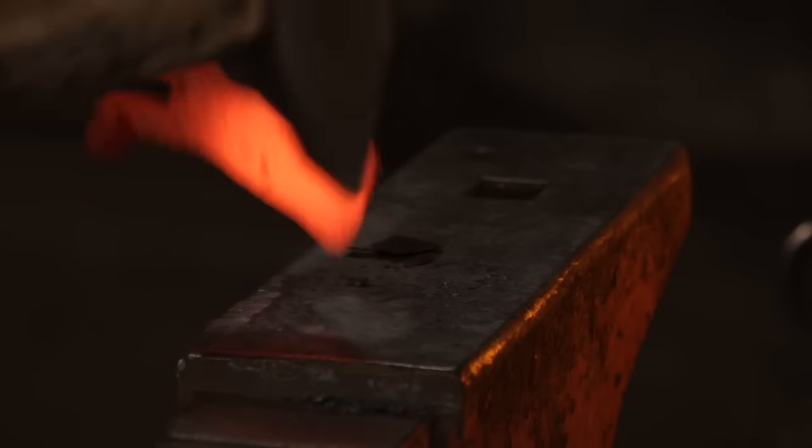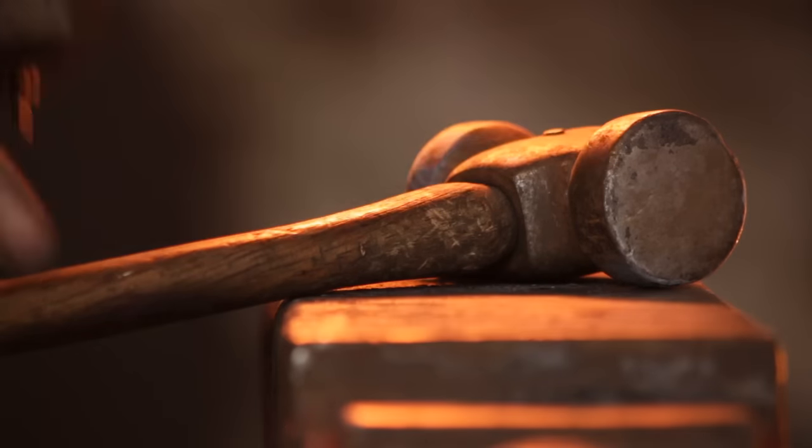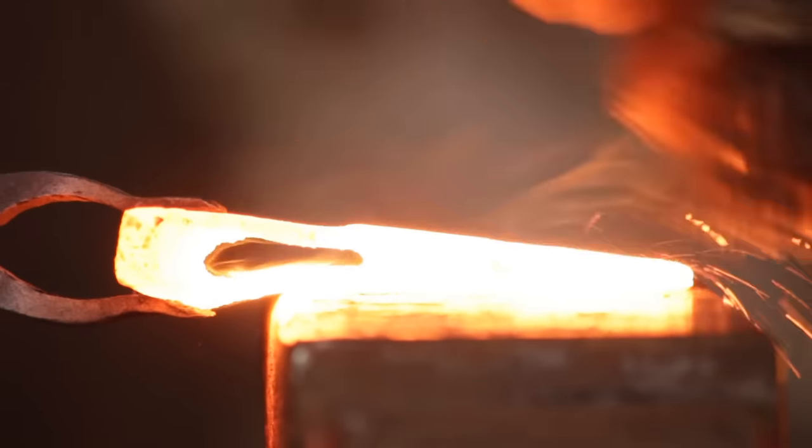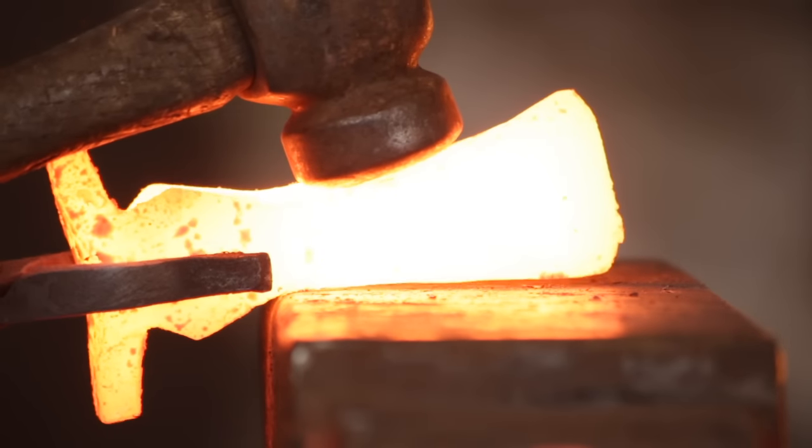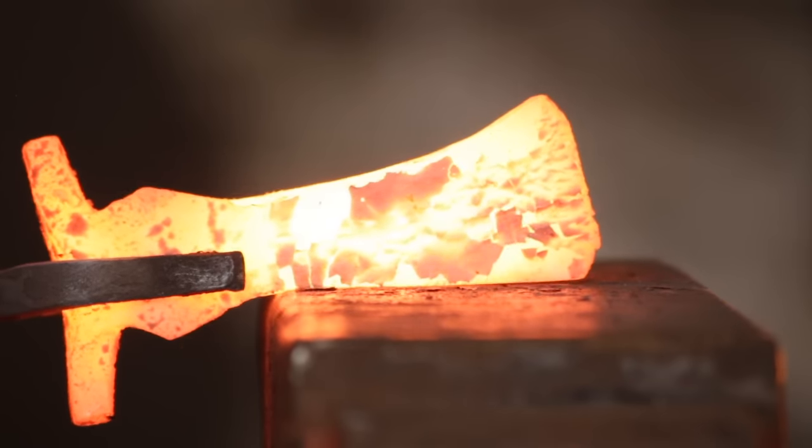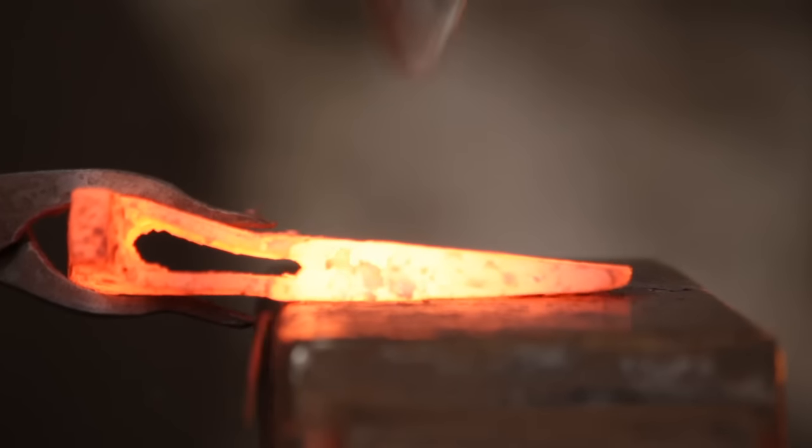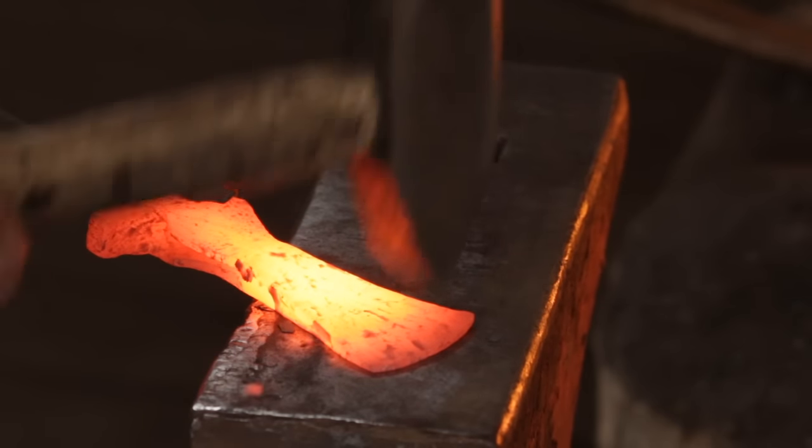So once that's welded up, spread it lightly with the cross pein. Just start dressing the overall shape. As you can see I'm going in with a turning hammer. I'm just dressing that curve just to make it a bit more attractive. So the other way you can see if a weld has gone in is if it's actually visible on the outside of the seam. Which as you can see it's not actually visible. You'll see it better on the finished product at the end of the video.